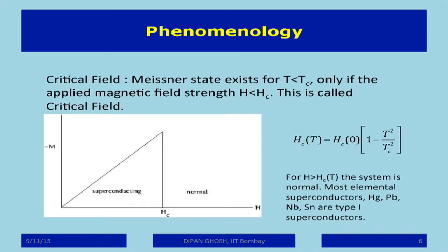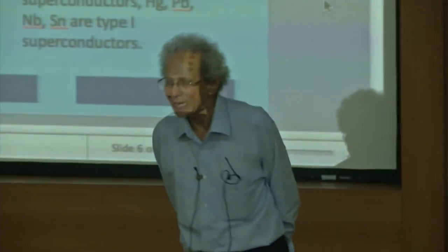Now, if the value of the magnetic field that you have to apply to remove the superconductivity at temperature T equal to 0 is Hc0, then the field that you have to apply at different temperatures depends on temperature as Hc = Hc0 (1 minus T squared by Tc squared). Obviously, if T is equal to Tc, you don't need any magnetic field to destroy superconductivity.